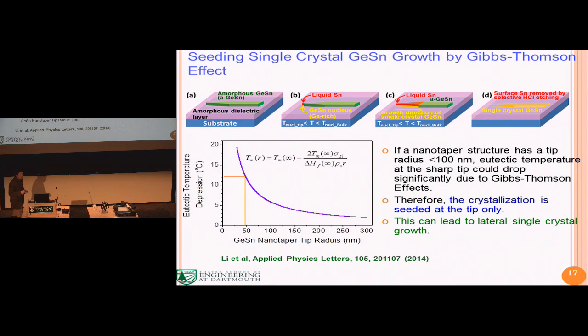So we want to move one step further. Can we really get single crystal material? Well, the key to get single crystal material is that you have to make sure you have a single nucleation spot, a single seed to grow the crystal. So we developed two ways to do that.